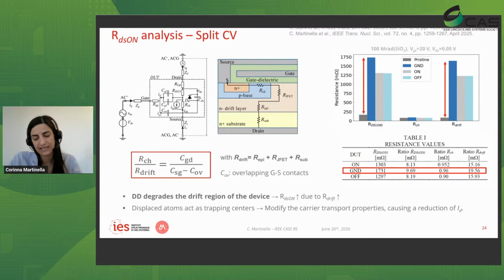And then by applying this methodology, we saw that this was all due to an increase in the drift resistance. And so this makes sense because in fact, we are maximizing the creation of defects in the substrate. And so it's creating a resistive layer in the substrate of the component. And so the drift resistance is increasing.